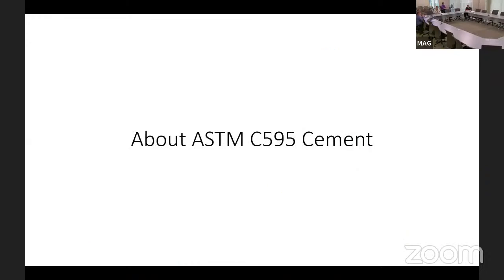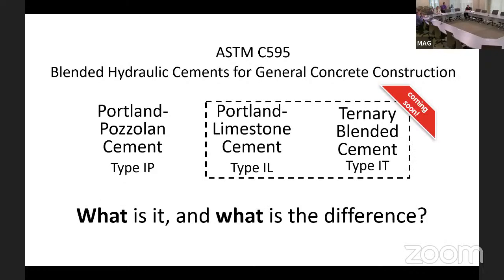So about ASTM C595 cement. ASTM C595 cement has been recognized and become very popular lately. There are 4 designations under ASTM C595: a Type IL blended limestone, a Type IP blended pozzolan, a Type IS blended slag, and a Type IT, which is a ternary. The ternary is a combination of 2 of the 3 SCMs, either the slag, pozzolan, or limestone. The reason for the popularity is it's a lower CO2 cement, so the carbon footprint is lower due to these replacement levels of clinker with these SCMs, which give you a significantly lower global warming potential on your EPD.